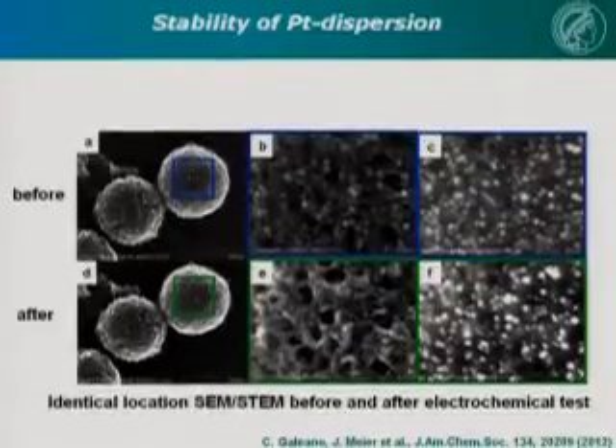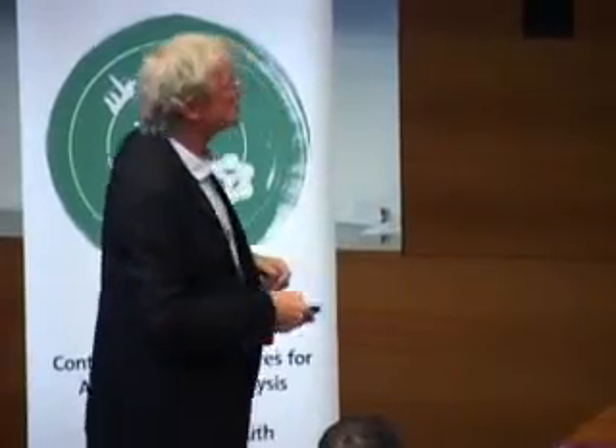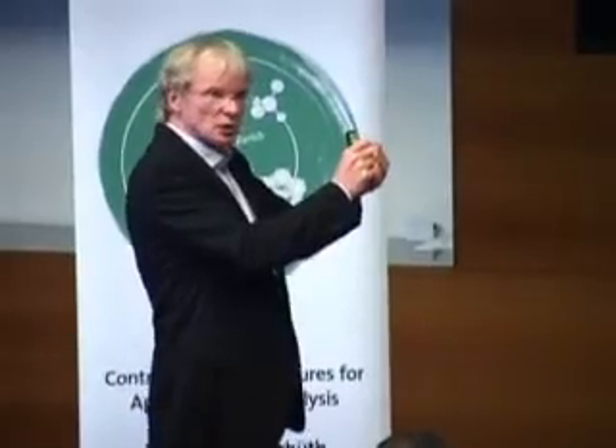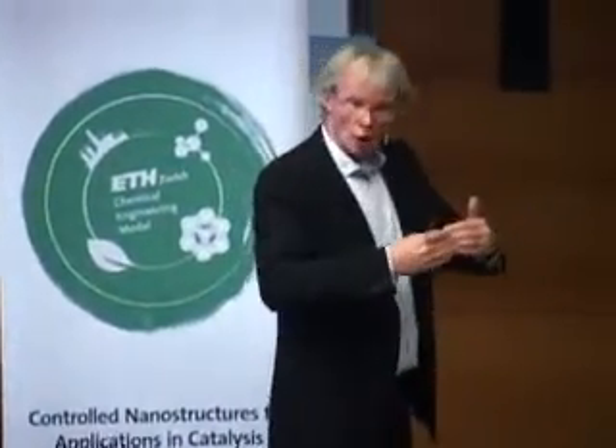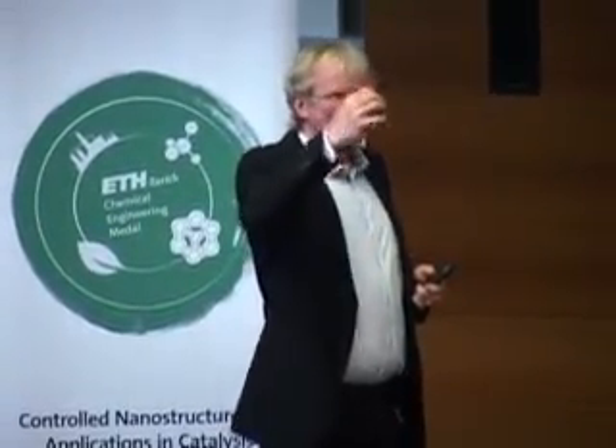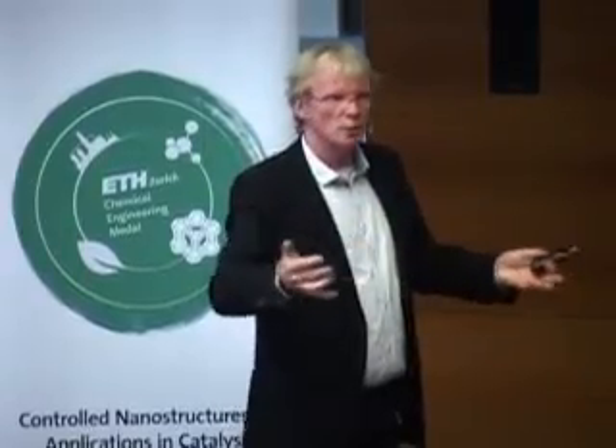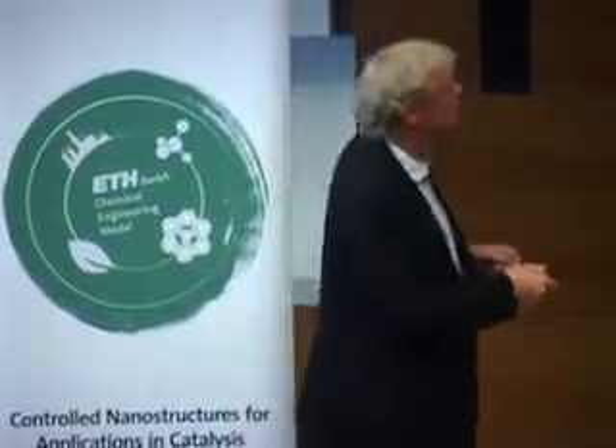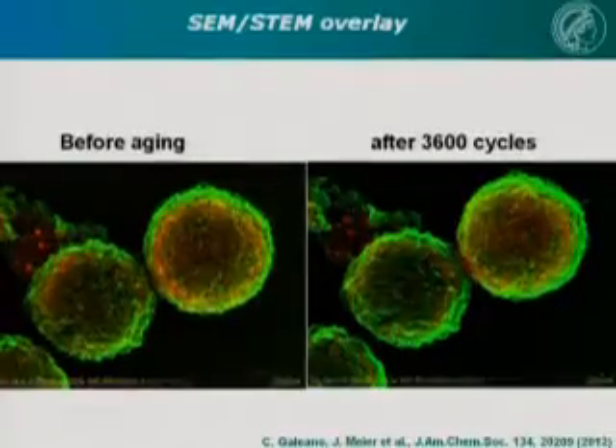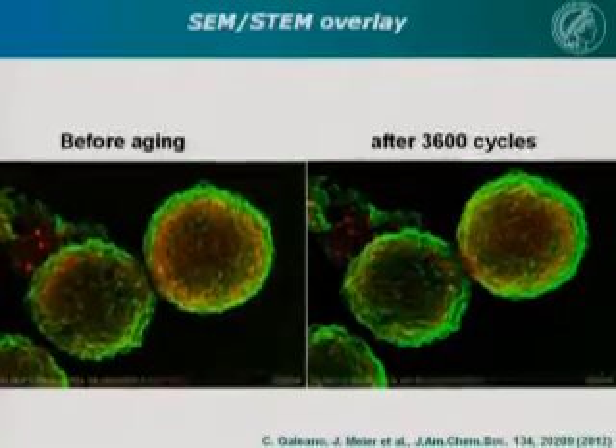I mean, you can still sort of see some of the pores here and here. These are the same ones, but the structure actually, the graphitic carbon actually corrodes quite substantially under the conditions of the electrochemical test, but since the platinum particles are confined in the pores, we don't lose them, they don't fall off, what normally actually happens. A major deactivation pathway is the noble metal particles just fall off the carbon support and then are just swimming around in the electrolyte. And this doesn't happen here, so we basically have the same performance afterwards. Here is again this nice overlay, it doesn't give you more information, just looks a bit nicer.